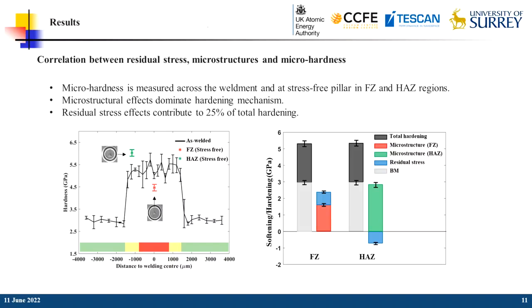We produce those residual stress-free pillars. We then apply the nano-indentation on top of the pillars. By doing so, the hardness values on the pillars will only depend on the microstructure. If we have a close inspection of the figures, we could find that although the total hardening is the same between the fusion zone and the heat-affected zone areas, the origin of the hardening effect is really different. The microstructure hardening is the dominant mechanism for the weldment.